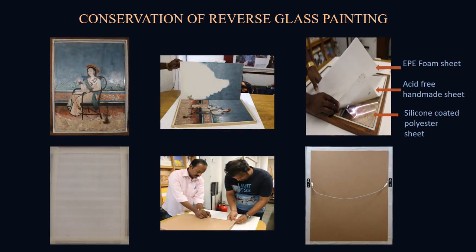Then the paintings were carefully put inside the frame. A silicone coated polyester film was given as a separator between the glass and the acid-free handmade sheet on which reintegration was done. An expandable polyethylene foam sheet was placed at the back for cushioning, and then a hardboard was given at the back. Finally, the paintings were framed in their original frames, which were also restored.